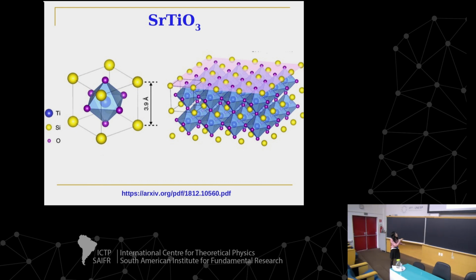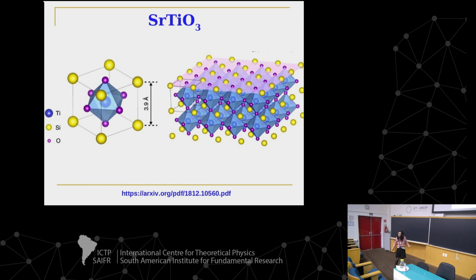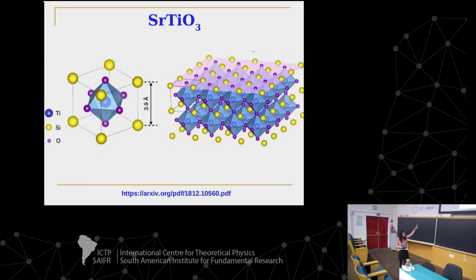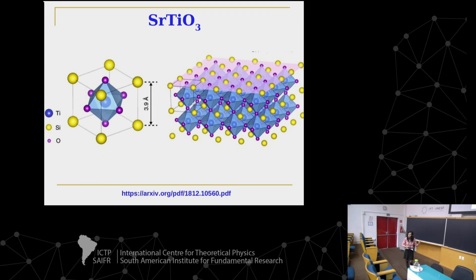And you can see that that's easy, because they are very symmetric. They start to bounce like dancing in the middle. And as these oxygens move, they make the fundamental crystal change from one format to another format, okay? The fascinating thing about this material is that usually when you work with solid materials, the transition from one structure to another is a first order type, meaning that it's very abrupt, boom, it changes. But because this is a dance of these oxygens, this becomes a continuous type of transition, and this material is very interesting for that.